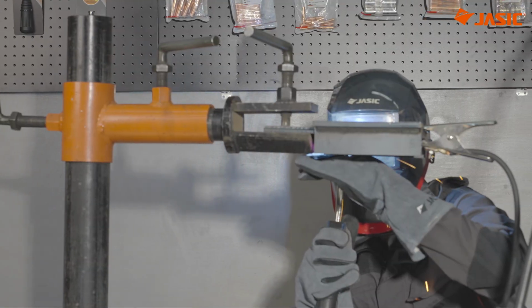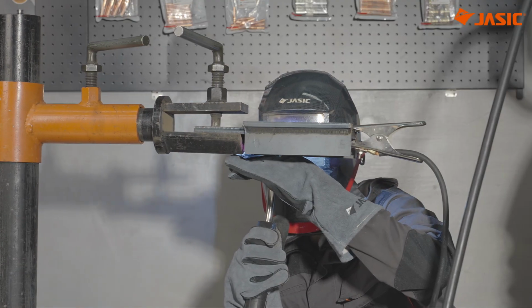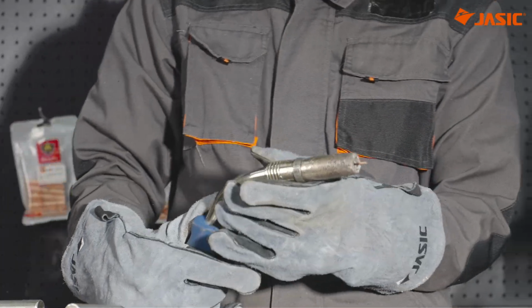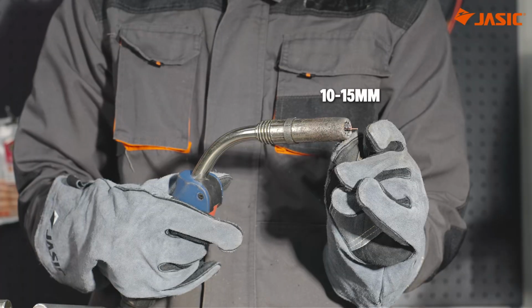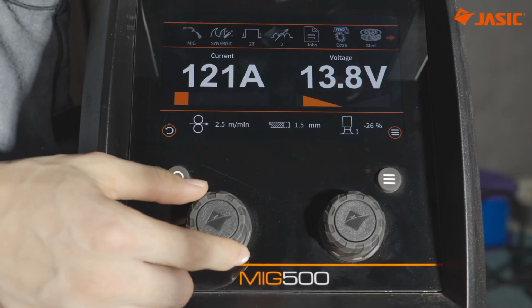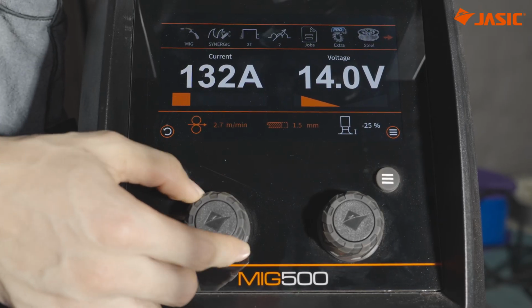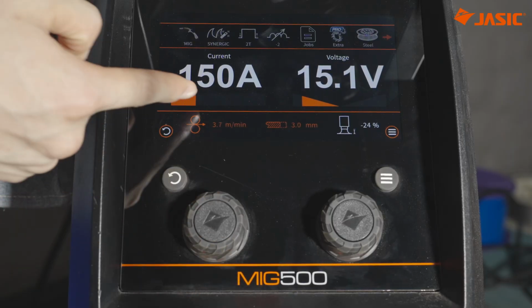In the overhead position, shielding can be more easily affected by air movement. And also, keep the stick out relatively short, generally around 10 to 15 millimeters. Too much stick out can make the arc unstable. Of course, the exact settings should always be adjusted according to your plate thickness and wire diameter.